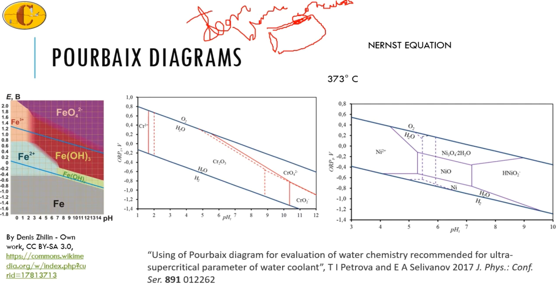So if in this case you have carbon steel, the basic element in carbon steel is Fe. The Fe has a variation with the pH as shown over here. Now, if you look at the potential from the EMF series, you will see that Fe has around -0.44 V at room temperature and at neutral pH, that is about 7. That is why at normal temperature the Fe will remain intact at its original standard potential. If we increase the pH at room temperature, at a high pH it goes into the region of formation of Fe(OH)2. Thus, if you have carbon steel at a high pH, you will have a film of Fe(OH)2, that is the ferrous iron hydroxide, on the surface.